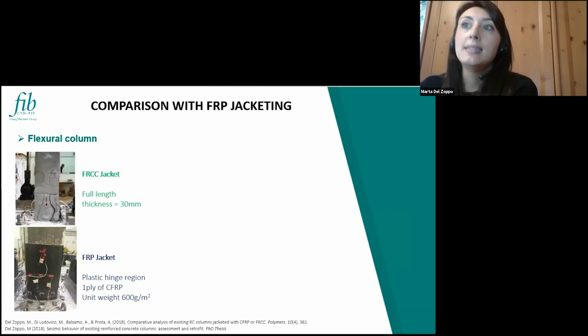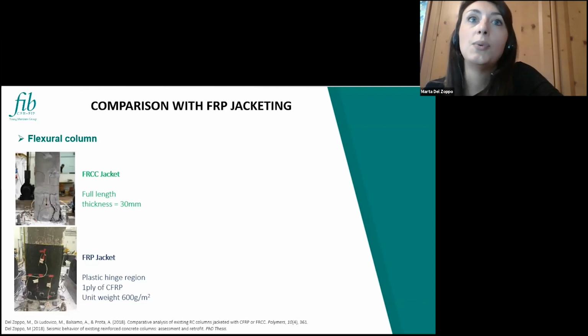So until now, we have seen and also understood how these materials behave when used as jacketing for members under seismic actions. And now we can see some comparison between this new jacketing technique and a more consolidated one that consists in the use of fibre reinforced polymer jackets for the members. So in this case, we are comparing for the flexural column, so the first application that we have seen, with the same column, in this case, jacketed just at the plastic hinge region with one ply of carbon fiber reinforced polymer with unit weight 600 grams per square meter.